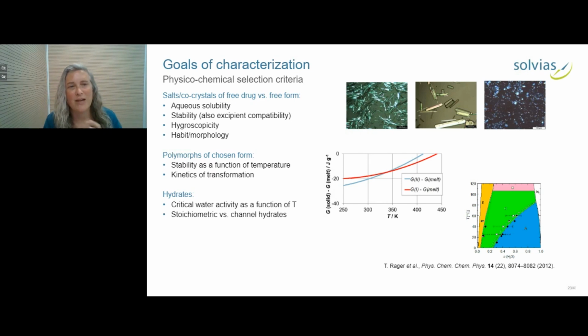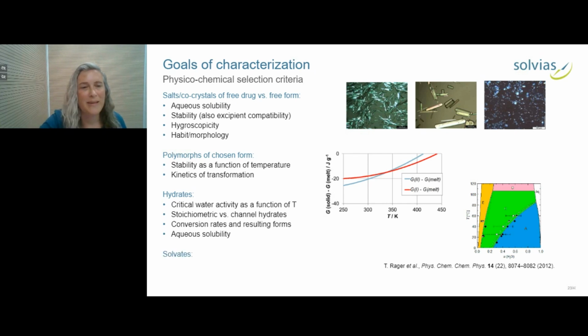You also want to see if your hydrates are stoichiometric hydrates or channel hydrates. Channel hydrates are a bit trickier to develop specifications for. And then you want to look at conversion rates and resulting forms. A lot of times when you dehydrate a hydrate, it goes into one amorphous form, and when you rehydrate it, it might not go back into the same form. So you need to understand, and this can be important for drying processes, are the transformations reversible or not? And then, of course, look at the solubility, because ultimately a hydrate's going to be the stable form in aqueous solution, and this could put a limit on your bioavailability.